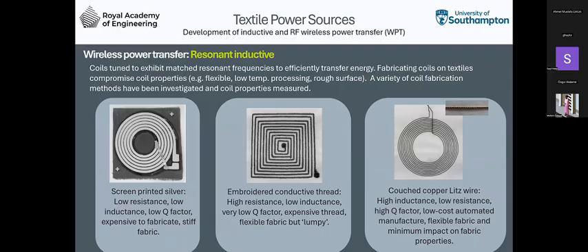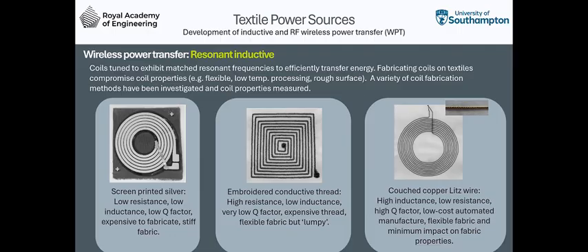Another form of powering the textile is to use wireless power transfer techniques. I think we're all familiar with the electric toothbrush that you put on a cradle and it wirelessly recharges the toothbrush. We can use the same principle with textile devices. What we actually use here is resonant wireless power transfer. We operate the coils at a resonant frequency, so they're tuned and they match each other. That vastly improves the efficiency of the wireless power transfer and increases the range over which you can transfer the energy. We are, however, constrained by the fact that the coil needs to be fabricated on the textile, and that produces constraints on the performance of the coil.